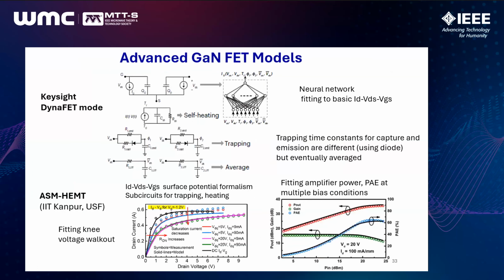self-heating primary effect. Now, in recent years, there have been significant improvements in the models that are available for nitride FETs, and a couple of them are shown here. For example, there's the GaN FET model from Keysight, which has subcircuits to indicate the trapping, and these properly account for the difference between the capture current and the emission current for both the gate and drain sources, as well as self-heating. Now, the overall IV curves are constructed by a neural network trained by lots of data.